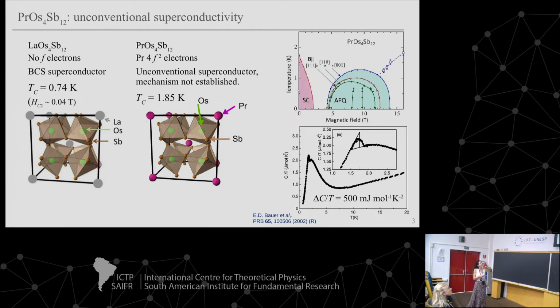So the idea, the crystal structures are very similar, and the phonons are very similar in these two materials. So it's expected that this one also has an electron-phonon pairing channel, but that there's another pairing channel on top associated with the F electrons that is making this superconductivity much more robust. I'm also showing you here the heat capacity as a function of temperature.